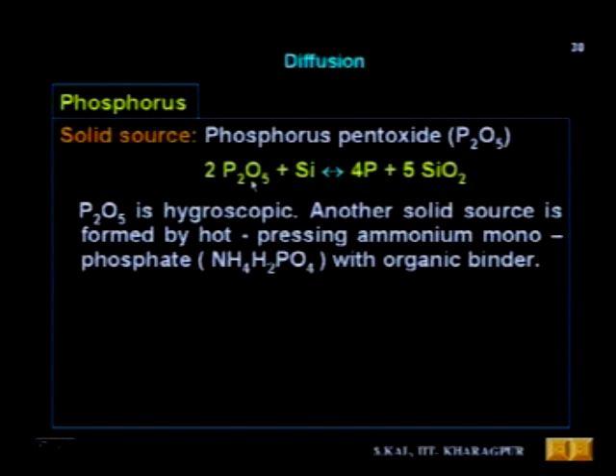So P2O5 is not used. Sometimes a solid phosphorus source is formed by hot pressing ammonium dihydrogen phosphate, NH4H2PO4, with an organic binder. That is again in the form of a cake, a thin slice, and its diameter should be equal to the wafer diameter. If you form that solid source by hot pressing, and then keep this solid source in close vicinity of the surface of the wafer, the same reaction will follow.